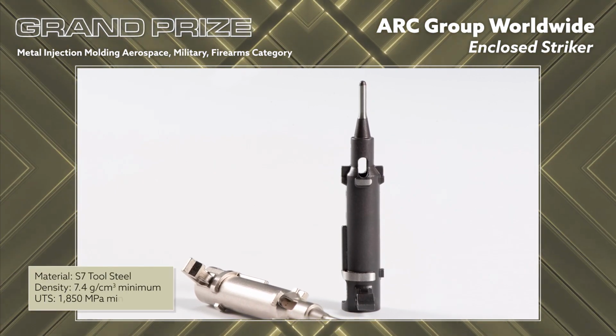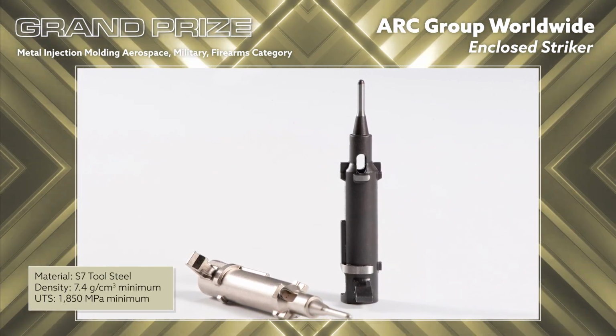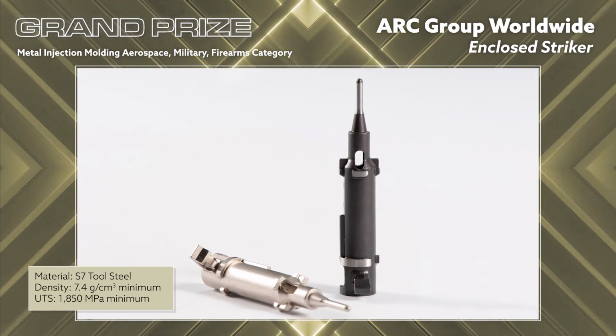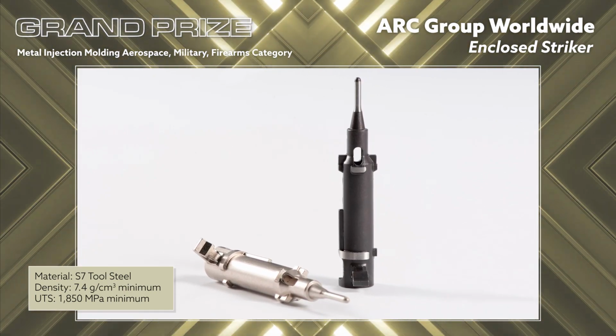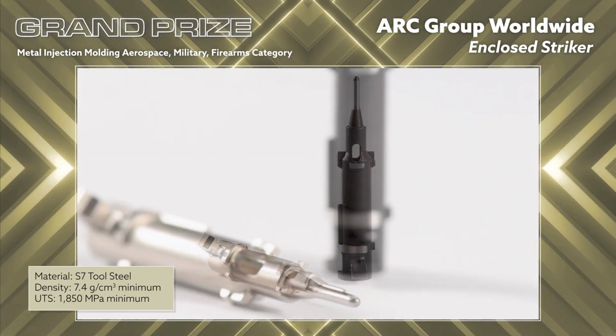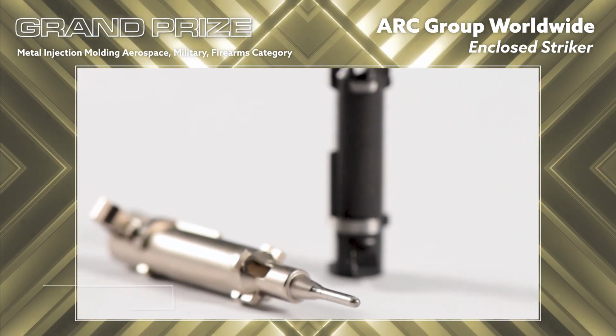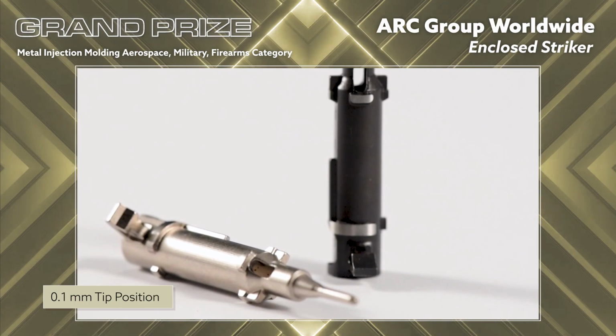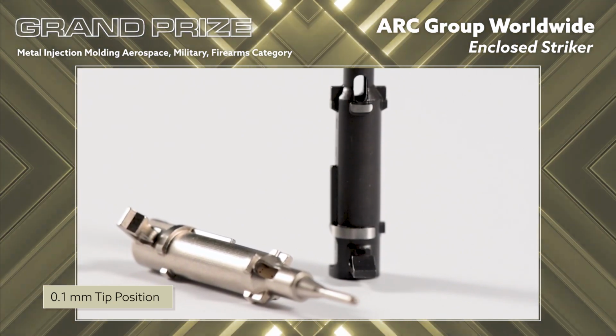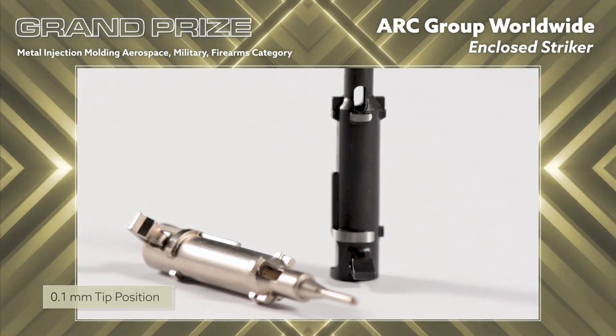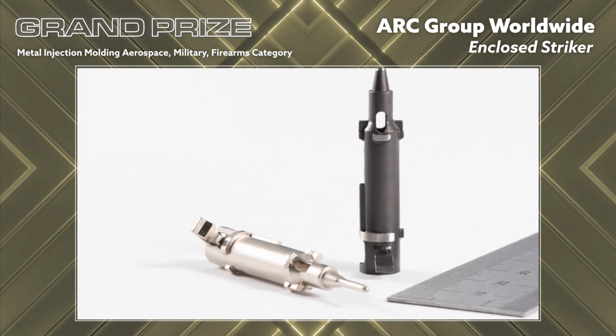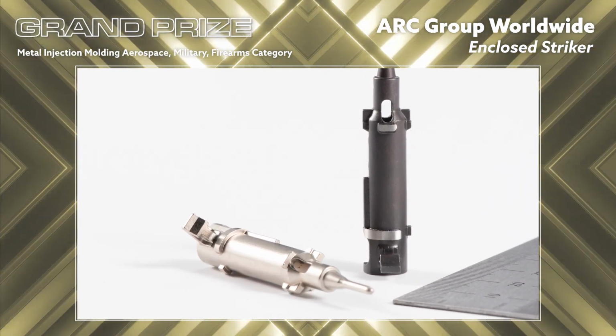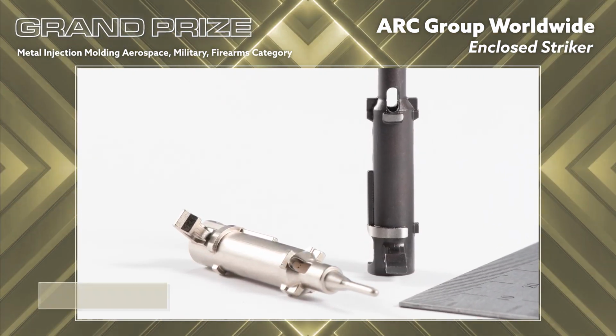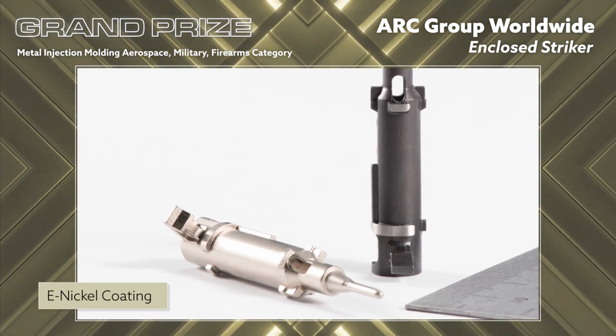Post-sintering, hot isostatic pressing and heat treatment are performed to increase mechanical properties. The parts are made using S7 tool steel powder processed to a 7.4 grams per cubic centimeter density minimum and a tensile strength of 1,850 megapascal. A 2-stage grinding process is required to achieve the 0.1 millimeter tip position specification. The grinding process includes machining the 2 main datum diameters on the body and the functioning tip of the striker. The position of the tip to the primary body of the component is critical for part functionality. The parts are finished with an electroless nickel coating.